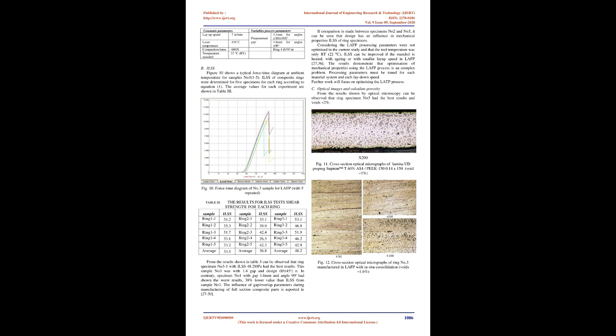B. Mechanical analysis. Short beam strength tests were performed for interlaminar bond strength characterization. In this study, the ASTM D2344 standard was followed. Samples were prepared using flats from the center where the process had reached steady state. The samples were cut carefully using precision diamond saw. The dimensions of the samples were within the tight tolerances of size according to standard ASTM D2344. SBS tests were performed with a universal testing machine. Load was applied with a rate of 1 millimeter per minute. Where Fm is the maximum force observed during the test in Newtons, B and H are the measured specimen width and thickness in millimeters respectively.